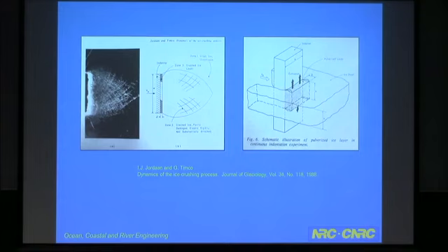They made an assumption from their observations that because they saw this crushed material here, that crushed material was through the full thickness of the ice. So they came up with this notion that there was a thick layer of pulverized material between the ice and the indentor, and that somehow that could create spall or create sawtooth load pattern and so on.